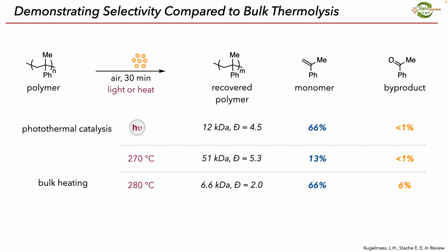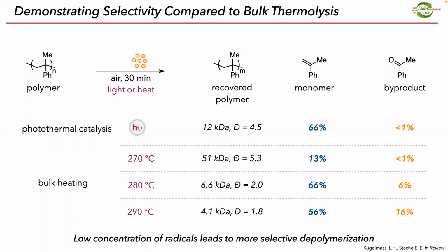If we heat this up another 10 degrees to 280, now we get comparable amounts of monomer formation, but now we're seeing this oxidized side product. And if we heat it up to 290, we actually see a decrease in monomer formation and more oxidized side product. What's happening is that with bulk heating, we're getting a higher concentration of radicals, and these are undergoing side reactions. It's in contrast to our method of photothermal catalysis, where we generate a very low concentration of radicals so it can selectively depolymerize back to monomer.